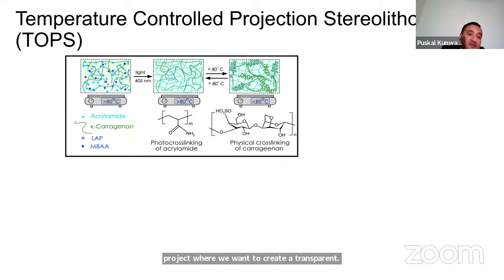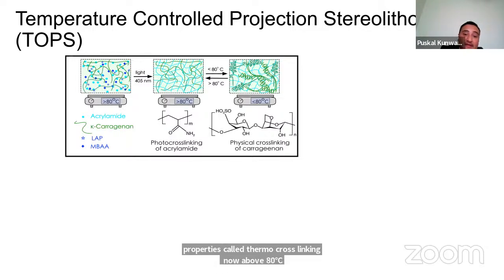So we replaced the alginate, which was the one giving us that opacity or translucent property, with kappa carrageenan. This is a polysaccharide mostly extracted from algae, and it has a property called thermal cross-linking. Above 80 degrees Celsius, it is a solution; below 80 degrees Celsius, it forms a gel. We still use acrylamide, LAP, and MBA as the photo cross-linkable crosslinker. We only changed to kappa carrageenan.